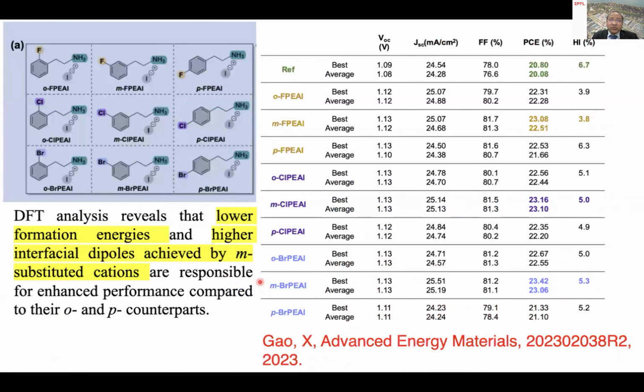Now, are there other cations? Yes, we have several of these cations. So here is the library of the cations we developed and measured. In this whole diagram, what I just want to show you is that the substitution has influence. It can be the fluoride, it can be the chloride, it can be the bromide, but also the position: is it in a meta position or para position or ortho position? So if you look at the data, in all the cases, the meta-substituted halide has a significantly enhanced efficiency compared to the blank. So this gives you an indication that the formation energy of the meta-substituted halide two-dimensional perovskite is lower than the ortho and para. And that's the information you can get from this type of study.